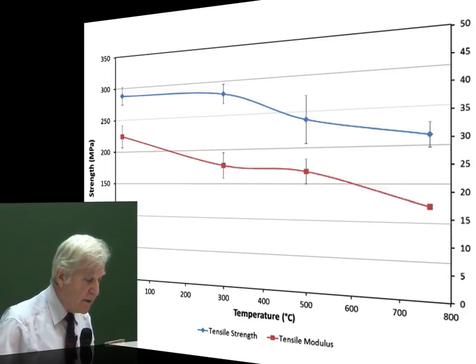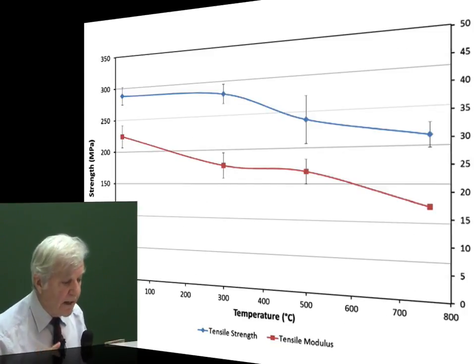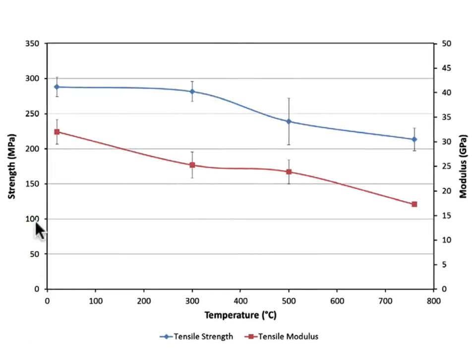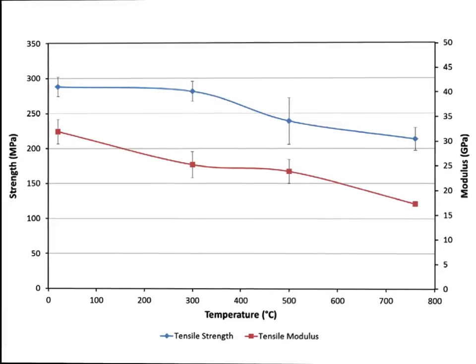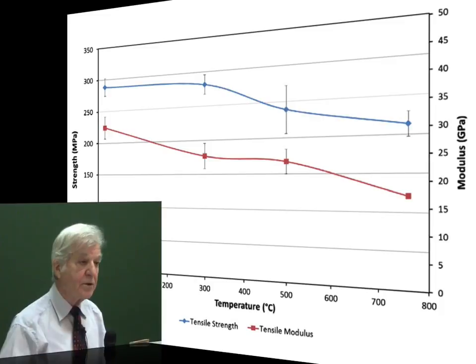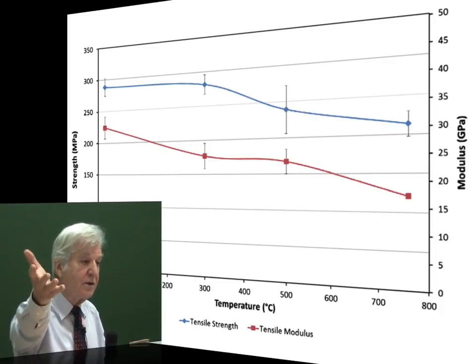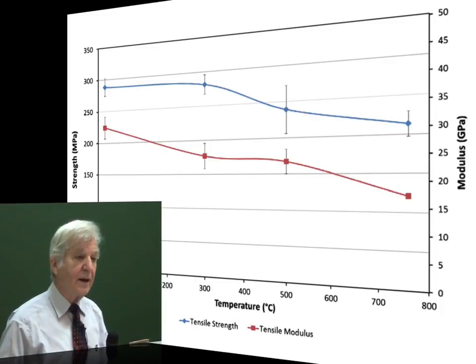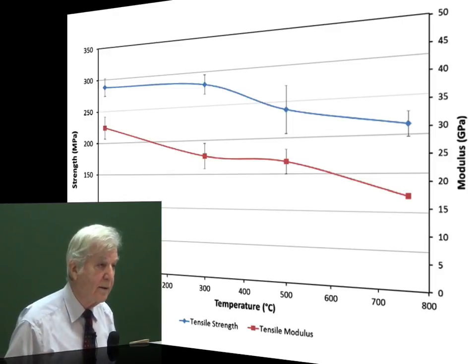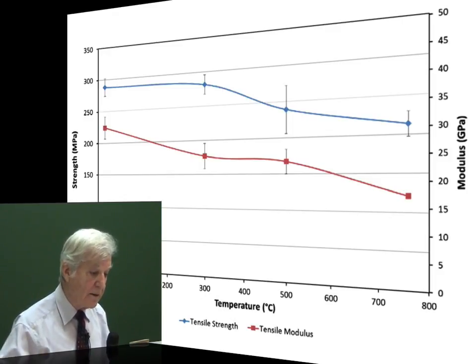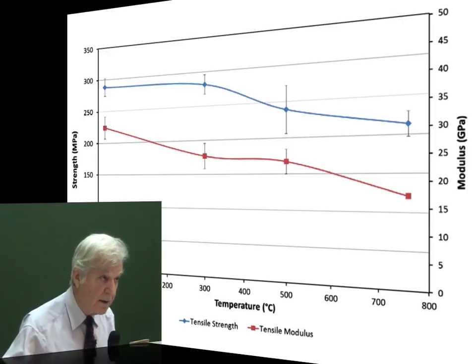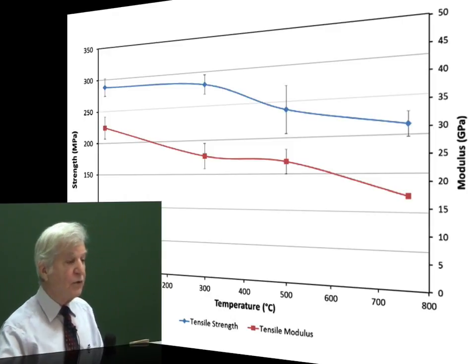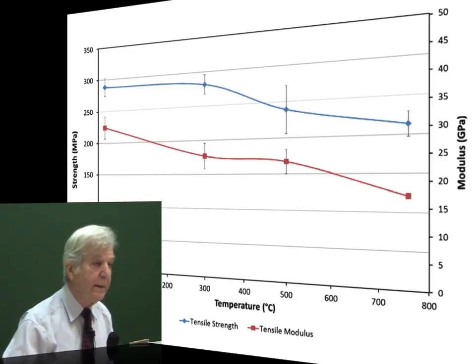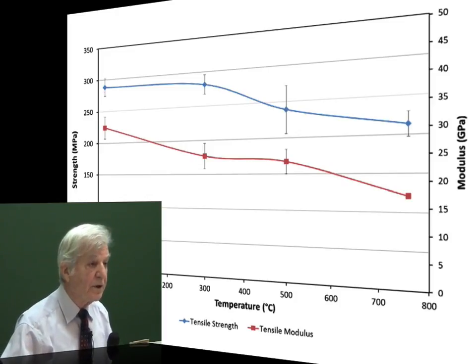So this is what they studied. It is the flexural strength with the temperature, but measured at the temperature. Usually you take a composite, put it in the oven at 800 degrees C, let it cool, and then measure it at room temperature. Here they measure at 800 degrees C, really. It was not easy for them, but this was the purpose, because this is what they are really experiencing.